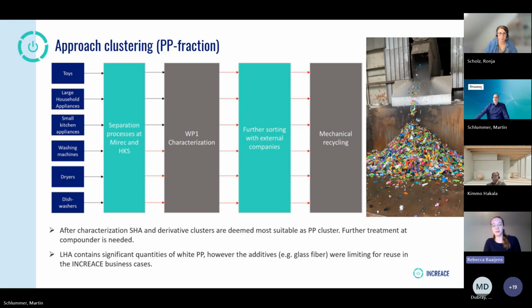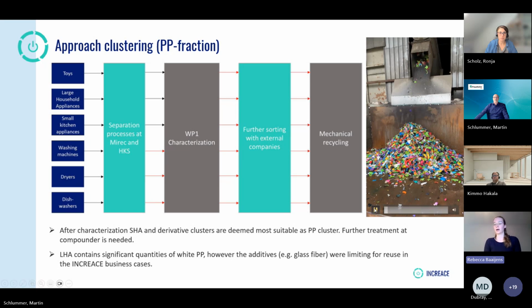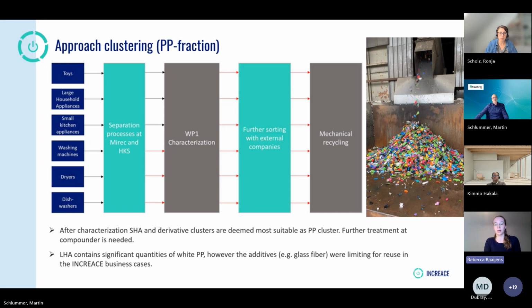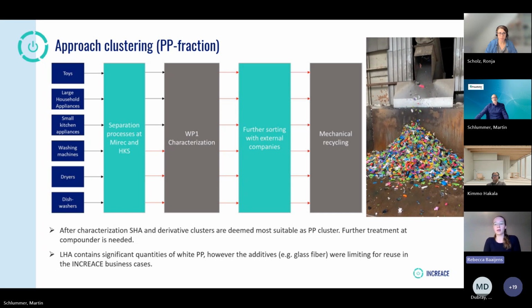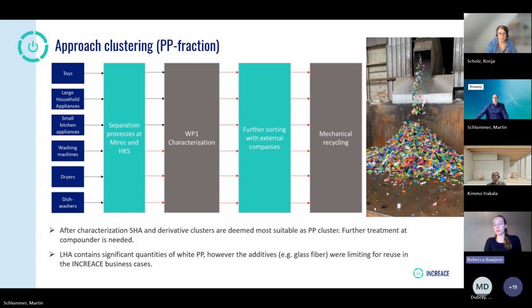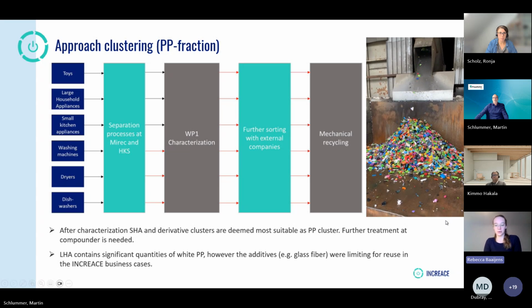If you can play the video on the right-hand side, that is the end step of how at MIREC, so that's the pre-processing mechanical recycler, we end with the floating fraction. So this is after we've processed a batch of only toys, hence the very nicely colorful mixture of plastics. But that also would mean for this batch that if you further process it, from what the KU Leuven found in terms of characteristics, it's a nice group, but it obviously comes with a color problem because it's all kinds of colors that you then mix to something that is in the middle of all of them.